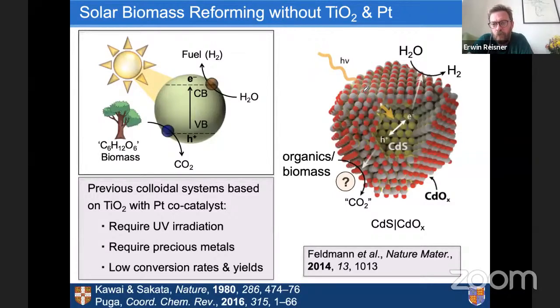And that's important because if you do photocatalysis with cadmium sulfide under more benign conditions, it will photodecompose or photo-oxidize or photocorrode, however you want to say, quite quickly. It will just precipitate as a black powder. But being in the alkaline solution protects the cadmium sulfide, and you also form this oxide shell. This oxide shell, we hoped, has similar properties to the titanium dioxide shell, and it's actually a decent catalyst, at least with reasonable conversion, to convert some biomass.